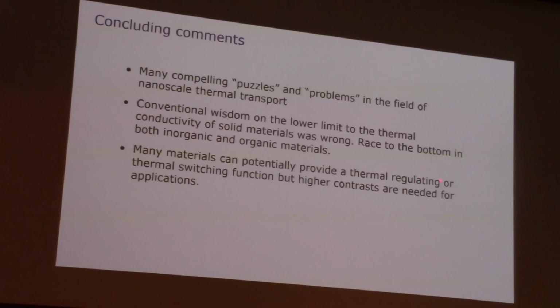And I would say many materials could potentially provide thermal regulating, thermal function. We certainly would like to find materials with higher contrasts. Could there be an application? It turns out we worked with the Toyota group also on that shape memory alloy, and they filed a patent on it. I don't know that it's particularly practical, but they wanted to protect the idea. The idea is that you would have a material where you're operating, say, a battery, and it would be somewhat thermally insulated. It would heat up better to get to an operating point. Then the material's thermal conductivity would go up, and the battery's temperature would be managed, right? And so, where do you find things like that, both materials and applications, that could move the field forward? So, thanks.